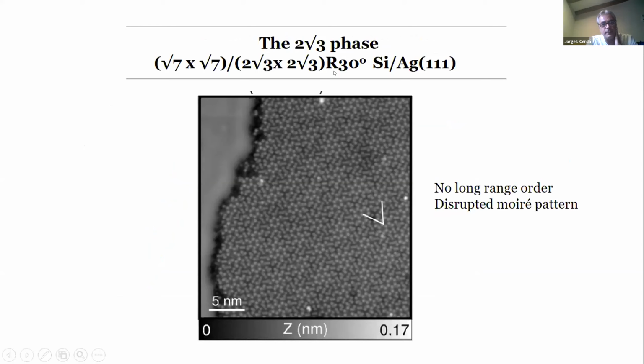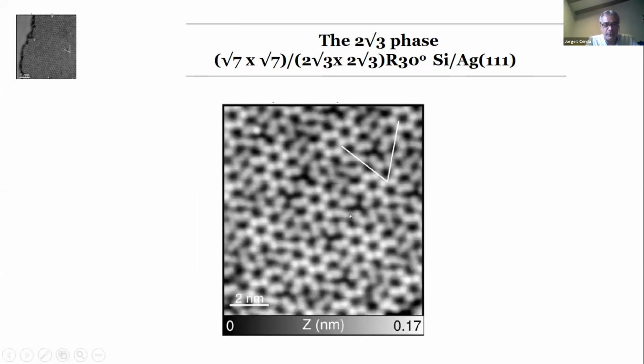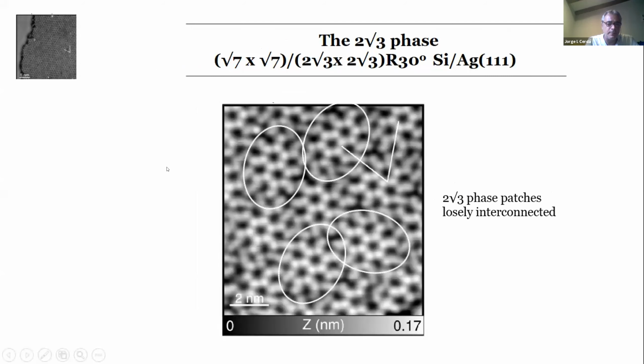Now we move to a different phase. This is a 2 square root 3 phase. It's also quite well known, although there's been a little bit of debate. It's basically a square root 7 by square root 7 for silicon and 2 square root 3 for silver. It is not very well ordered. It does not have really long range order. It's kind of a disrupted moiré pattern. If you look at the high resolution STM images, what you find is some patches where you can see the reconstruction very nicely, but also they are loosely interconnected with many imperfections around.